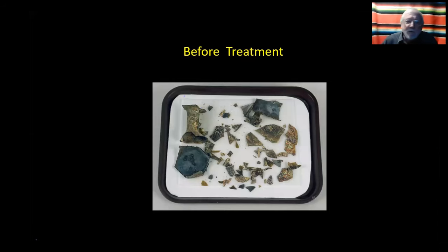So this has a very large base, which is solid and quite strong right here. And you start adding fragments around the exterior of the base. And with B-72, you don't have to do anything complicated with your adhesive. You just apply it to one edge, you put the piece on, you press it and squeeze out the excess adhesive, and you're basically done. You don't pull the pieces apart. You don't re-wet them at this point.